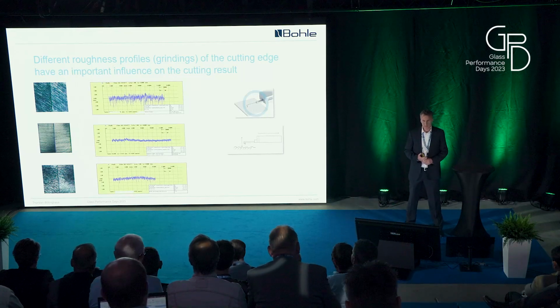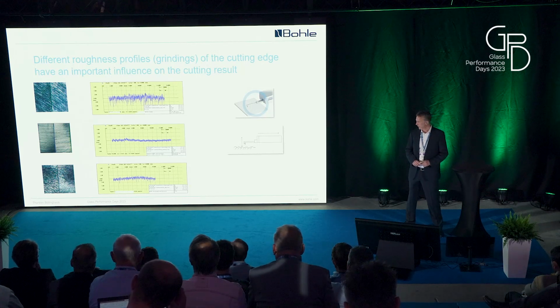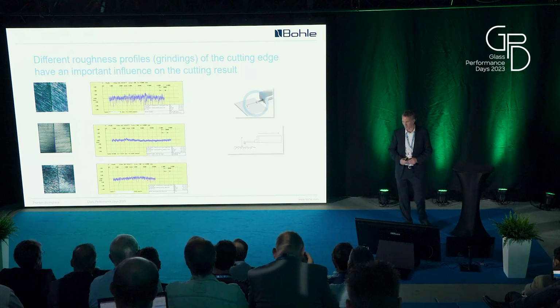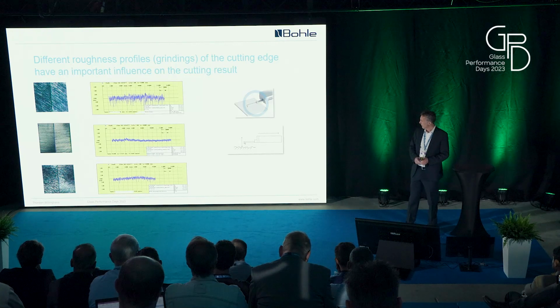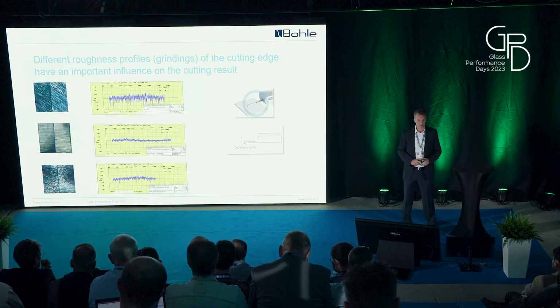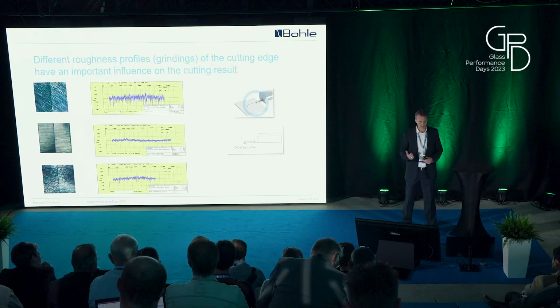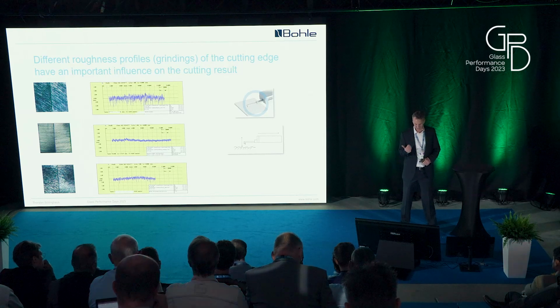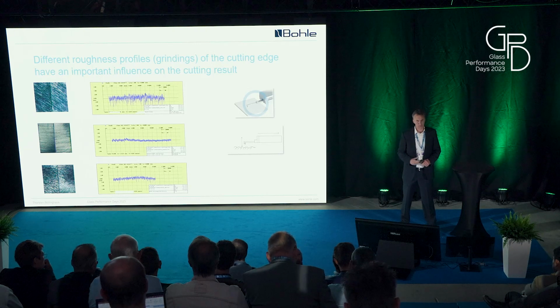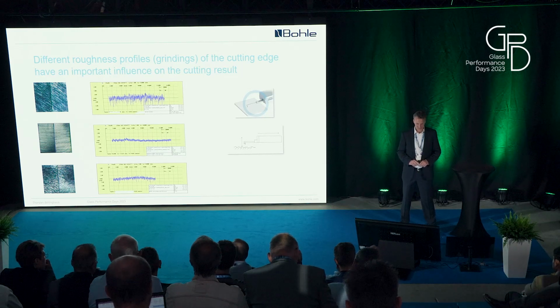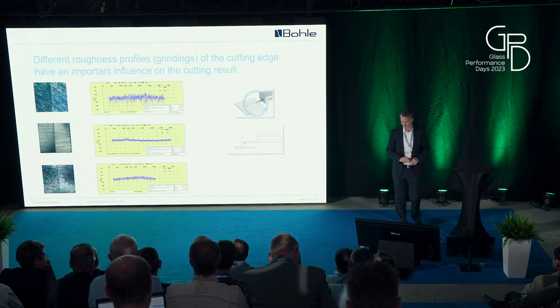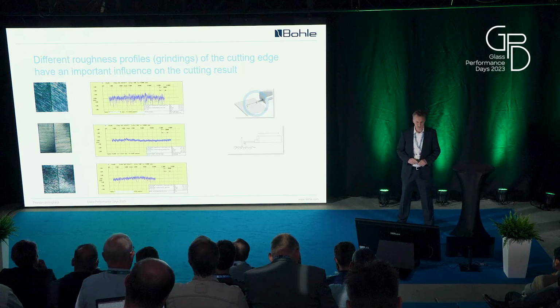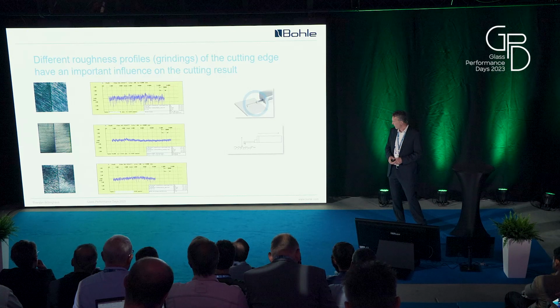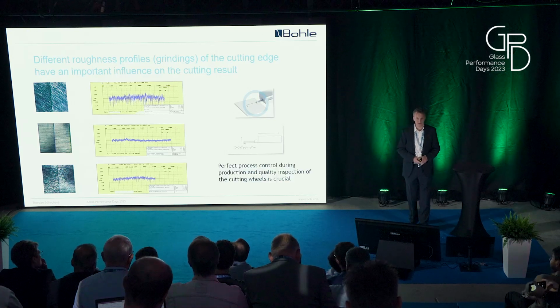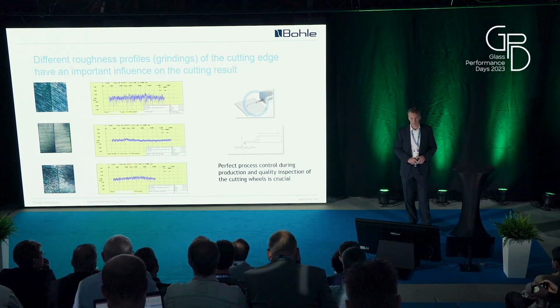Another important point is the grind of the wheel, which gives the roughness. On the upper picture you see a very rough grind, and on the picture below you see the roughness profile. This has to be very well controlled because it's like riding on a bumpy road, but vice versa: the wheel is bumpy and the surface is flat. You give pressure peaks to the glass below and you get a much more aggressive cut. So if you have to induce high tensions into the glass, you will choose a grind like that. If you have a very low sector and very thin glass, you will rather take a grind like you see in the middle. The production of the cutting wheels and the process parameters need to be very well controlled, and quality inspection needs to be very tight.